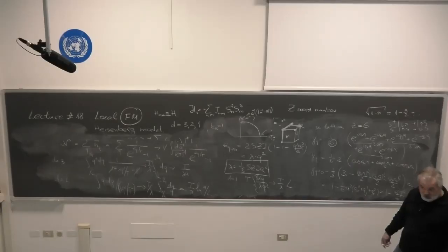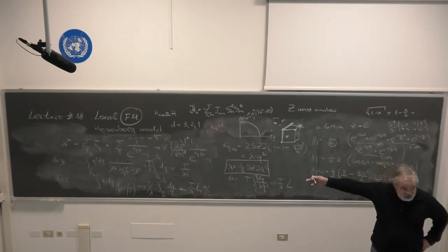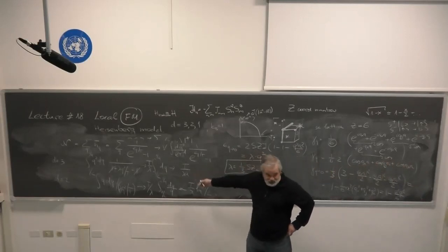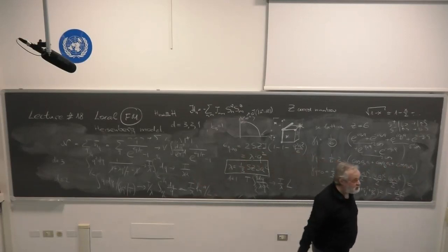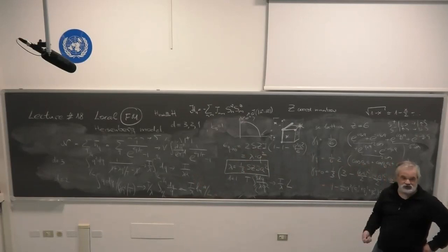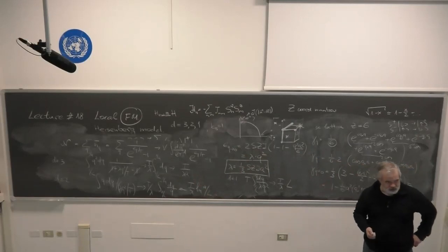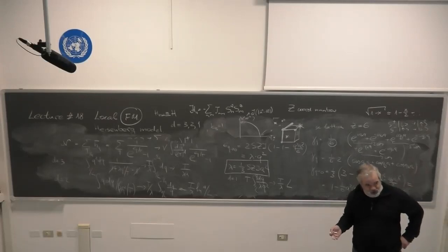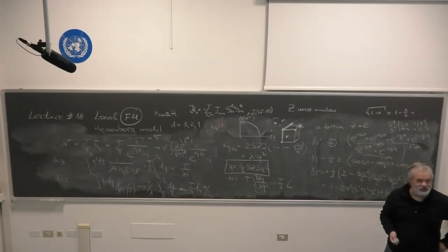So since it diverges with the system size, you cannot have long range order because of that divergence. Yeah, because the number of magnons scales with the system size. Yes, and for 3 dimensions, it is not sensitive to system size. You can send your system size to infinity, take the thermodynamic limit, and you get a final result. Here, the number of magnons grows linearly with the system size. For a 2-dimensional system, it grows logarithmically, but luckily there is a coefficient, temperature, which controls this behavior. So if temperature is equal to 0, despite the logarithmic growth of the number of magnons, it is nullified by zero temperature.